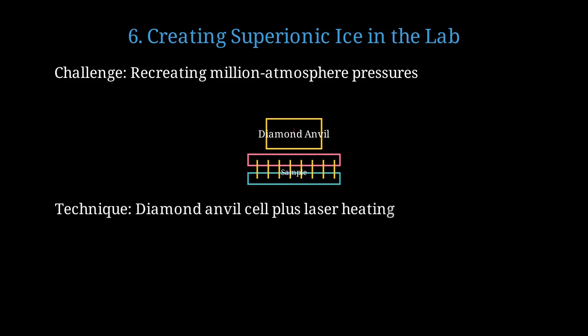They combine diamond anvil cells with powerful laser heating to simultaneously achieve the high pressure and high temperature needed. The experiments reach about 2 million atmospheres and 5,000 Kelvin, matching conditions inside ice giants.